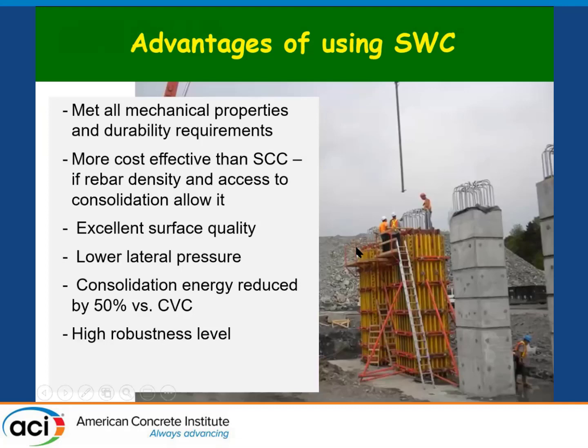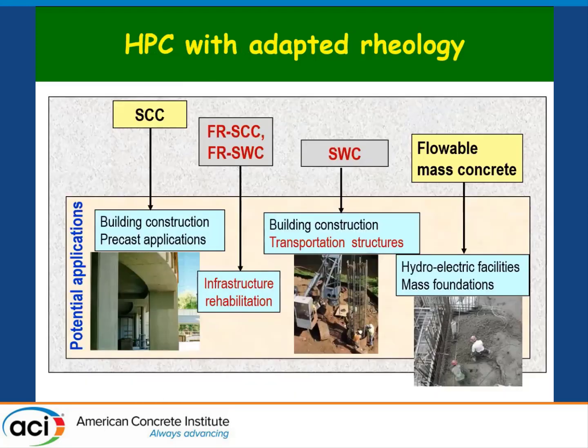Despite the very high casting rate, about 30 feet per hour, the form pressure was much less than anticipated. So there are many advantages of using superworkable concrete. In this case, the concrete that was designed met all the mechanical properties and durability requirements. It was more cost effective than SCC, but providing that the rebar density allows it and the access to consolidation allows it, which is not always the case, as you know. Because of the internal consolidation, excellent surface quality was achieved, low pressure. Consolidation energy was, compared to conventional vibrated concrete, reduced by about 50%. And this type of concrete, given other studies, proved to be very robust.